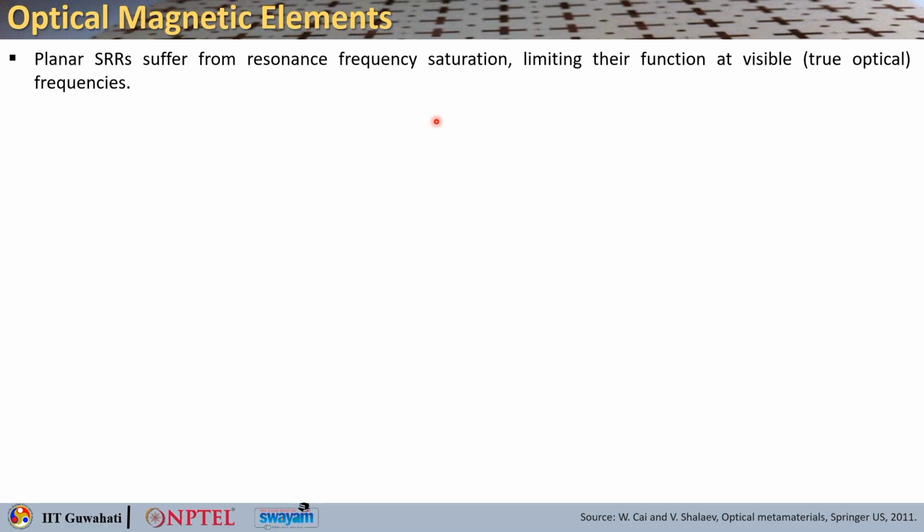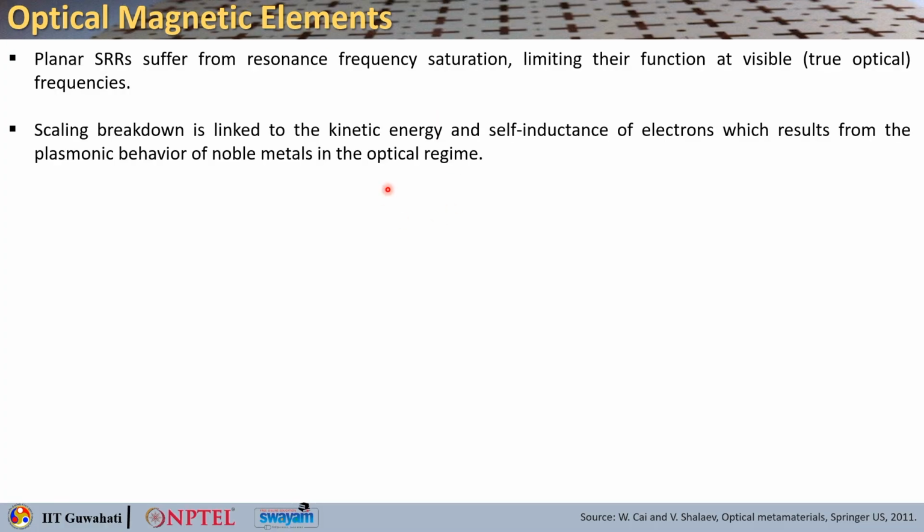So, you cannot keep on scaling it down and move the resonance frequency to the optical regime or even higher frequency, that will not work. This saturation effect fundamentally prevents the SRRs from providing magnetic response at the true optical frequencies, which is basically the visible range.